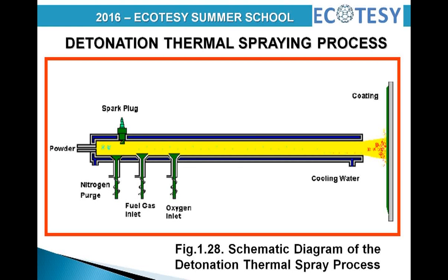The detonation thermal spray process efficiently uses high kinetic energy and temperature of detonation wave and controlled thermal output to produce dense, very low porosity coatings that exhibit very high bond stresses, some exceeding 350 MPa. The coatings have low residual, fully controlled internal stresses and can be sprayed to thicknesses not normally associated with dense thermal sprayed coatings. The detonation gun basically consists of a long water-cooled barrel with inlet valves for gases and powder.